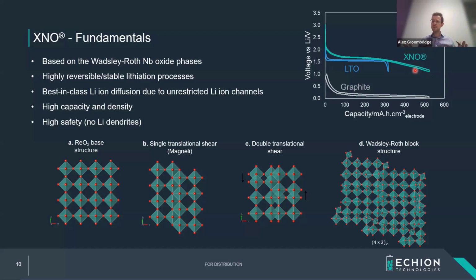Safety-wise, there's a fundamental safety here shared by LTO and XNO. The voltage is higher, which means that you don't have any risk of lithium dendrites when you try and fast charge. If you try and fast charge graphite, you have overpotentials leading to voltage dropping below 0, and you end up with this lithium dendrite formation, which is a real challenge to manage for fast charging. Those are the materials in general.